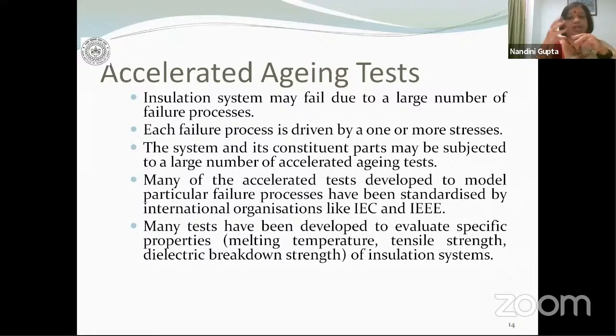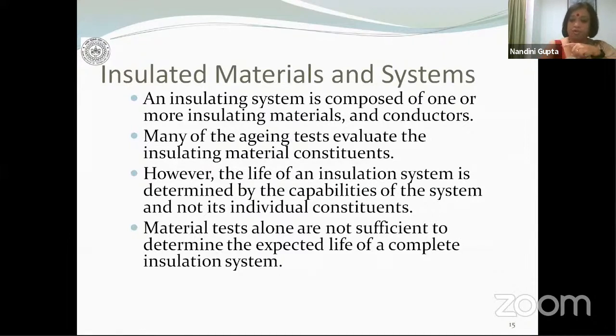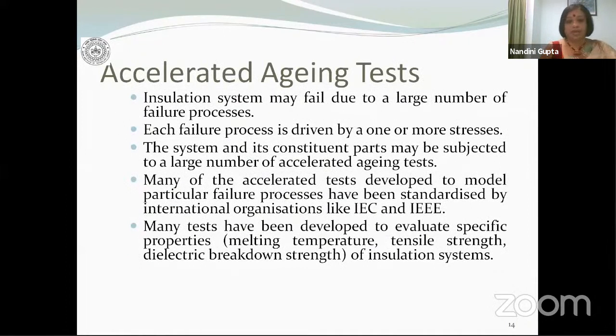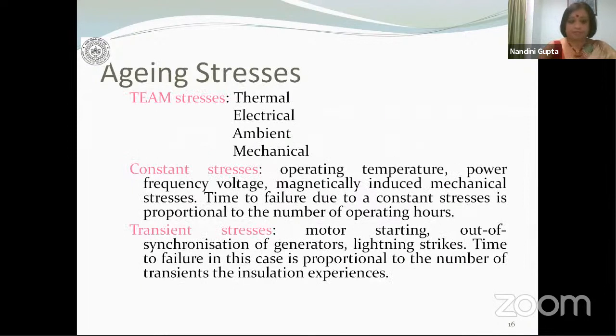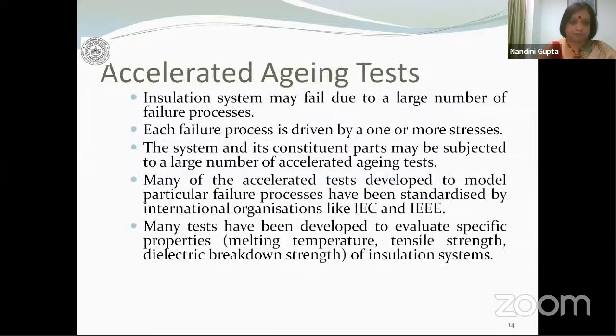When the conductors get overheated, the insulating materials surrounding the conductors will get overheated. Now, insulating materials cannot dissipate heat that fast. Conductors have high thermal coefficients, so the conductors will expand, but insulators have low thermal coefficients, therefore they will not expand so much. So firstly I have a thermal process, a thermal stress. As a consequence of this thermal stress you have expansion, and as a result of expansion, there is mechanical shear between the insulation and the conductor.